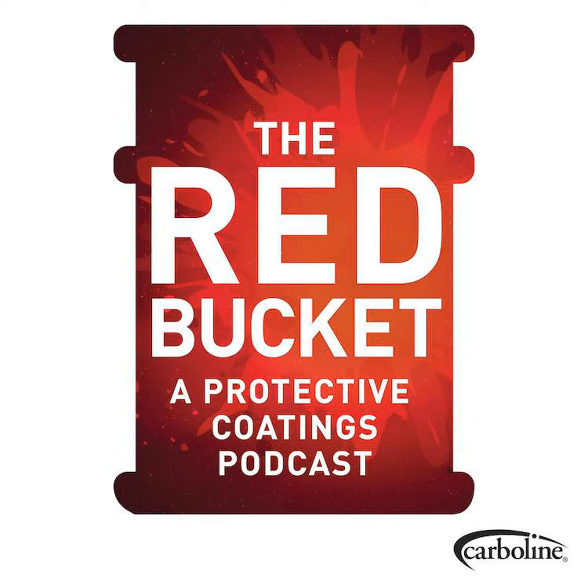and for carbon steel actually. In such an unpleasant environment, I wonder, is there a generic way to describe the normal or standard lining technology for a molten sulfur tank car? Most folks have gravitated towards Novolac epoxies or even phenolic type epoxies, something that has high heat resistance and overall high chemical resistance, because that is one aspect of this service that's important, not let alone the corrosion resistance aspect of the lining itself. You have to be able to withstand the physical conditions, being the heat, primarily as the breakdown mechanism, but then also the physical abuse that can happen to those coatings. So that's where those Novolac epoxies, phenolic epoxies have really been the go-to products, I would say, for